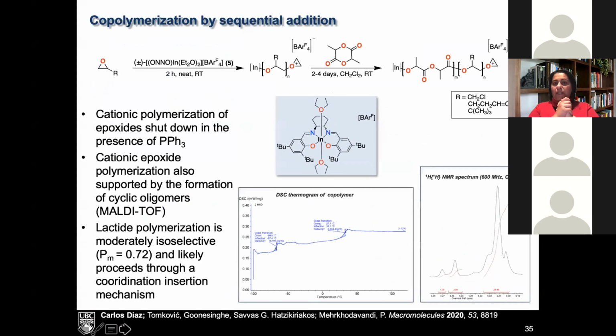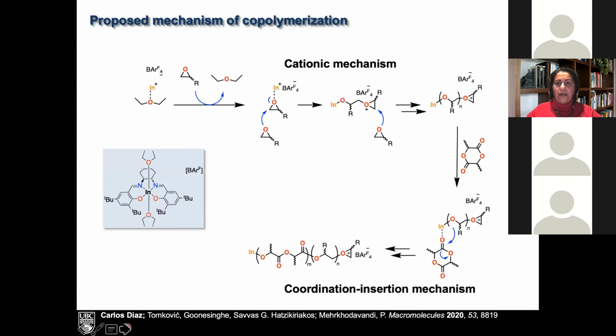But what my student Carlos showed was, if you change the nature of the counterion, previously the counterion was hexafluoroantimonate, and if you change this into BARF, all we have done is change the counterion to BARF, and now what we're getting is a block copolymer. You can see that from the fact that you have two different transitions in the DSC. This has to do with the fact that you have a different mechanism in this case. It is a cationic polymerization, and when you're thinking about cationic polymerization reactions, you always have a cationic chain end, and the nature of the counterion becomes really, really important in this case.